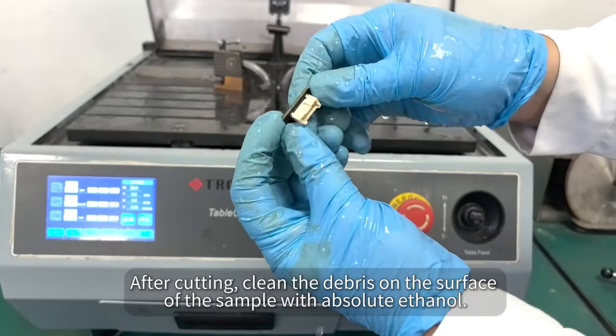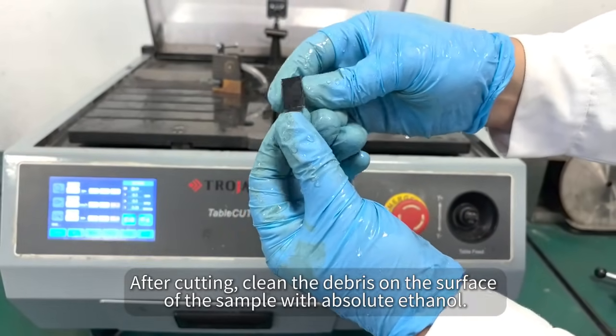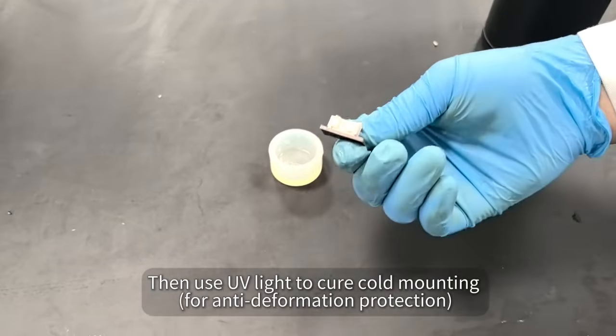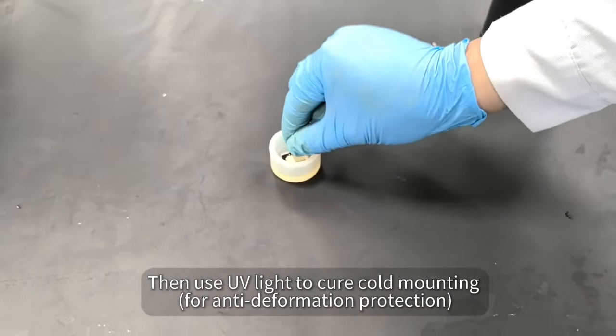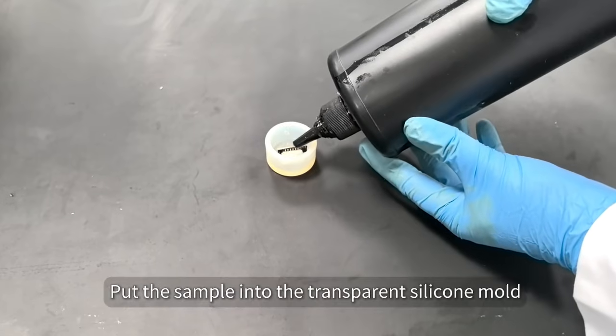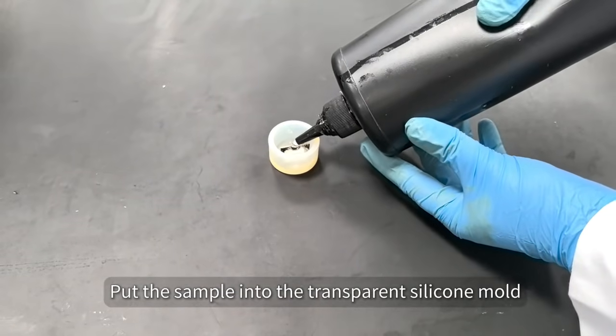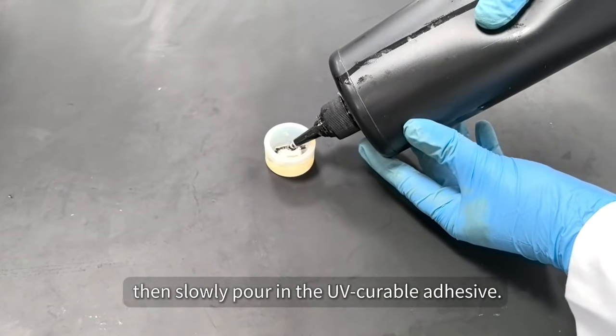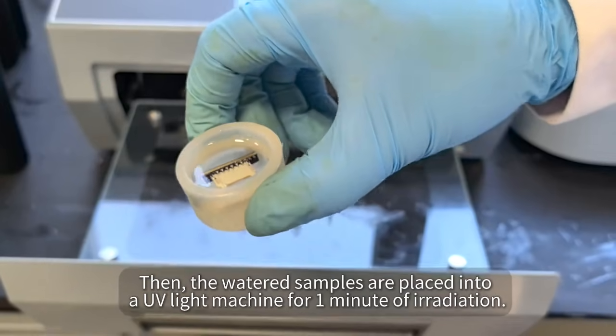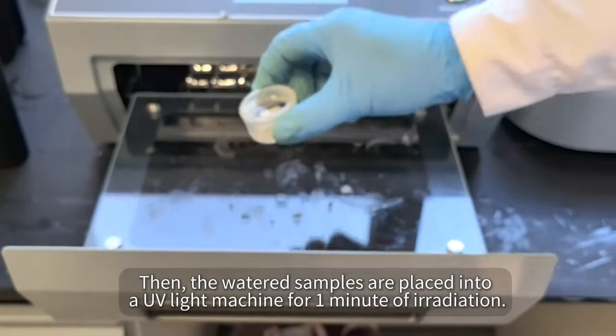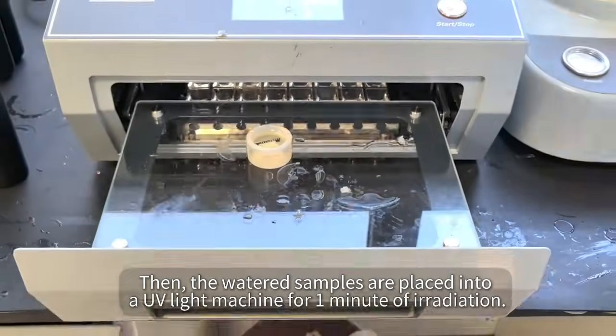After cutting, clean the debris on the surface of the sample with absolute ethanol. Then use UV light to cure cold mounting for anti-deformation protection. Put the sample into the transparent silicone mold. Then slowly pour in the UV-curable adhesive. Then, the filled samples are placed into a UV light machine for 1 minute of irradiation.